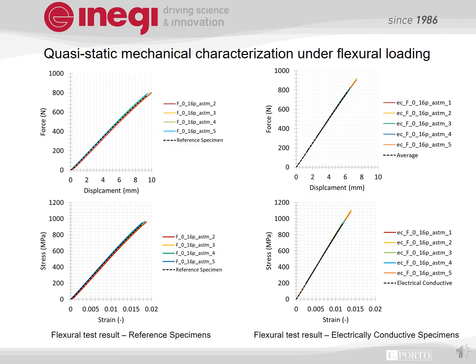Quasi-static mechanical characterization under flexural loading. Reference and electrical conductive test specimens were tested using the test method described. All the test specimens showed reproducible results. Total energy absorbed by each specimen was equivalent, as seen from the area under the curve of the force-displacement graph. The graph on the left-hand side shows the result from the reference specimen, and on the right-hand side shows the electrical conductive specimens.